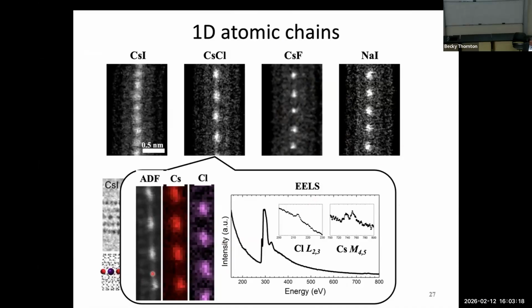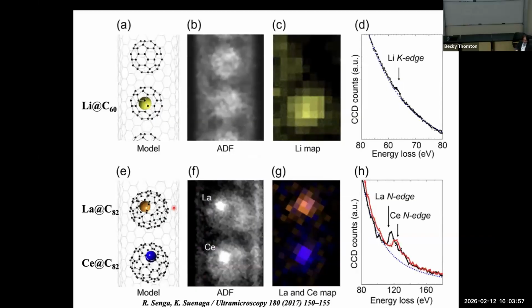This is a chemical map that we could make from that spectra. As you can see, you can see cesium atoms and chlorine atoms there. Chlorine is a bit light, and you may not see it between two cesium atoms in the ADF map, but if you make a chemical map, you clearly see that. But the important thing is that the size of the atom is different. If you see the size of atoms in the ADF map versus the cesium atom, this is a little bit bigger. So why is this happening? This is the so-called EELS signal delocalization. As you can see in other examples, if you make a map of lithium, the lithium map is very big. This is for lanthanum and cerium, but they are a little bit bigger than the ADF map.